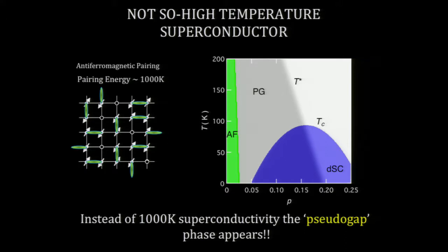But you don't. What you really have, as you see in this phase diagram, is that once you start to put holes in, which is described by p, you enter this pseudogap phase. And superconductivity only really sets in once you pass 5% doping. And even the highest temperatures will be somewhere around 140 Kelvin, nothing up at 1,000 Kelvin up here. So this is why we don't understand what is in these compounds.